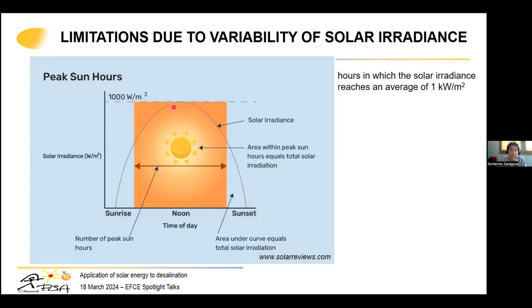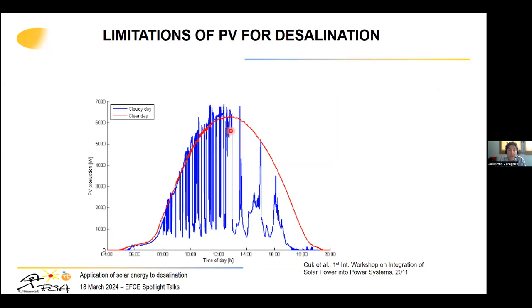So normalized by 1,000 watts per square meter, it's the equivalent number of hours in which the solar irradiance reaches an average of 1 kilowatt per square meter. So it's turning this area below this curve into this square. And the peak sun hours depend, of course, on the day, or on the season, on the position, the latitude and the place you're in. It is 4, 5, maybe 6 hours, best case. So that's the amount of radiation that we can use.